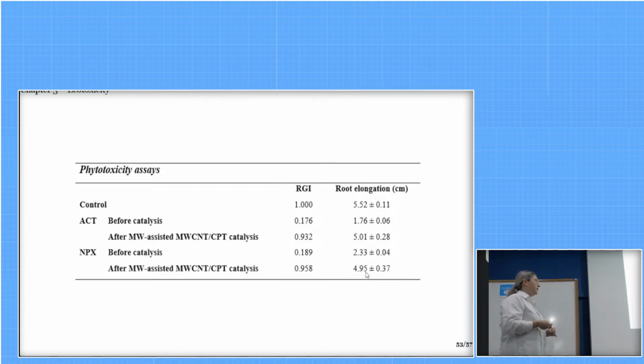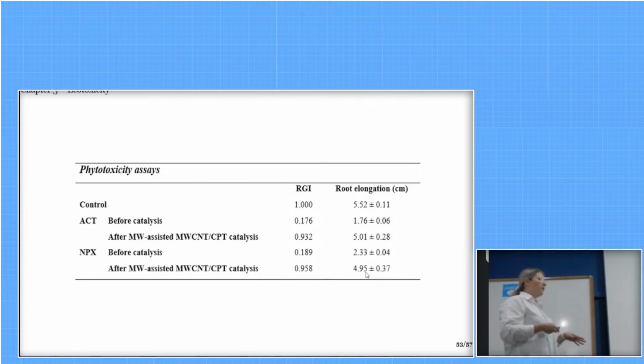So we carried out phytotoxicity assays for Lactuca sativa, which is common lettuce seeds, and we observed that after the treatment using the novel catalyst under microwave radiation, the germination growth was nearly similar to that in the control sample, and the root elongation was also very similar to the control group. As before the catalysis, almost no seed germinated, and the ones that did not grow even half the expected for the control group.